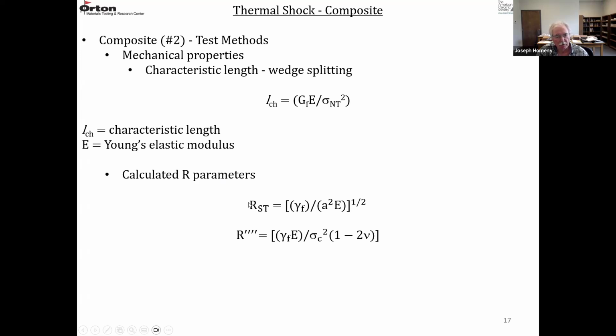So if we look at our R parameters, RST and R4 prime: RST was the fracture surface energy divided by the thermal expansion coefficient squared and then the Young's modulus, and that's all to the 1/2 power. But R4 prime was the fracture surface energy times the elastic modulus divided by the fracture strength squared. That is this formula right here. So this characteristic length is basically R4 prime minus this term, which contains Poisson's ratio. R4 prime, if you remember, was derived in a triaxial stress state. That's why there's a Poisson effect in this equation. So basically, the higher the R4 prime value, the better the thermal shock resistance. The higher this characteristic length, the better the thermal shock resistance.